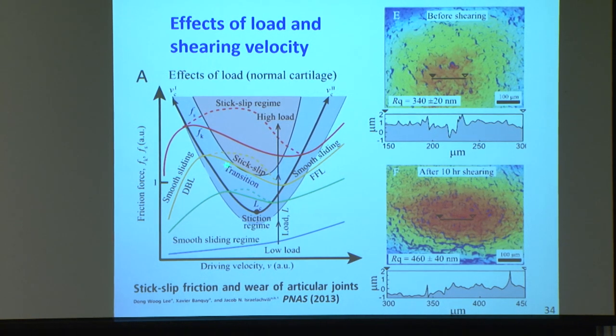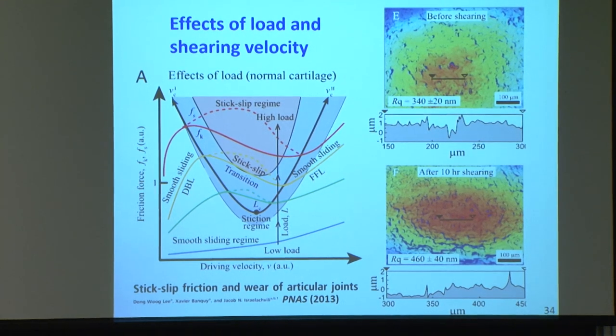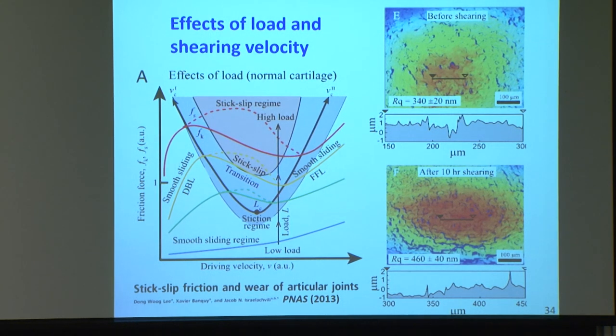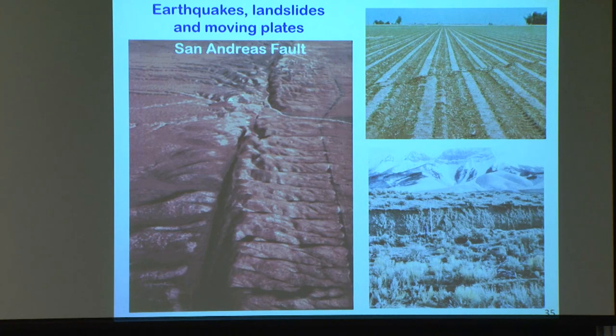What causes damage is this irregular, sudden, continuous jerky motion, and each time it's as if you hit it with a small hammer, and you give it all these knocks. The knocks may only be half a micron, but at the level of the tissues and the cells and so on, or any material, half a micron is a lot. And that's why you can have something stick slip, which is often ignored in measurements. People just measure the average. But that's what often is the important thing.